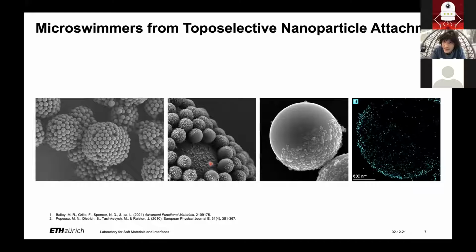This hemispherical coverage of nanoparticles, or in general of the catalytic film, is advantageous because the nanoparticles can't go towards the wax surface because of the densely packed monolayers, which you can see here. So the nanoparticles essentially can't reach the wax space because of the particles which are in the way. So this was quite a nice accidental finding.